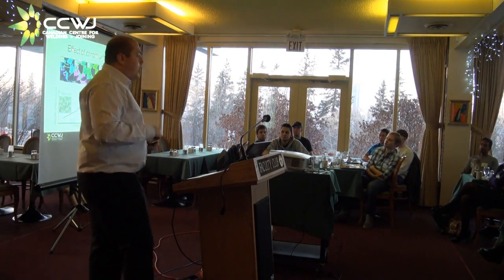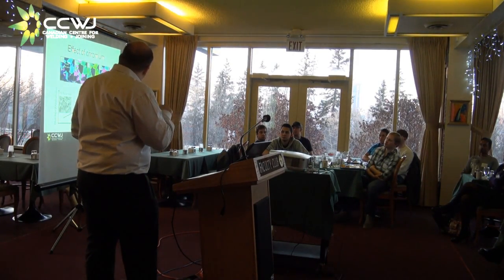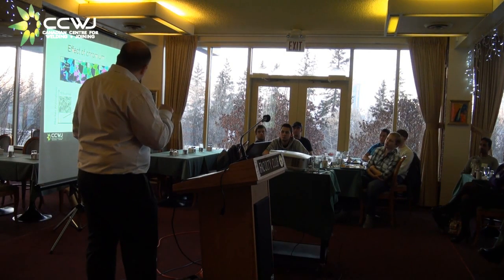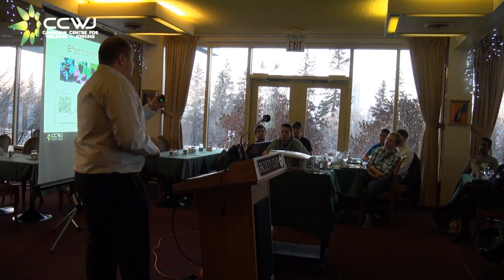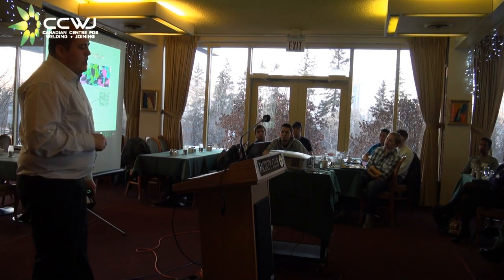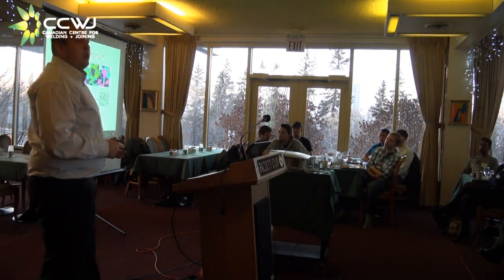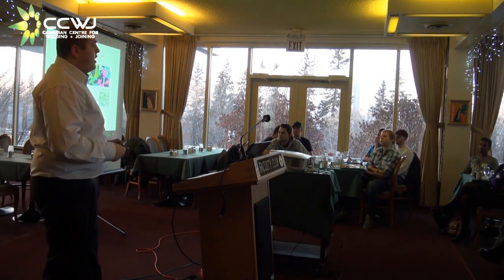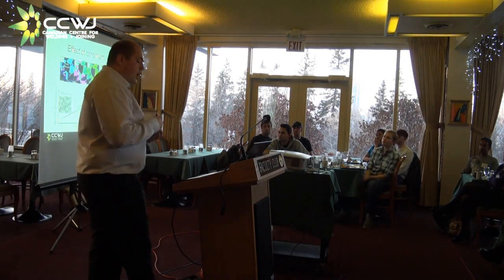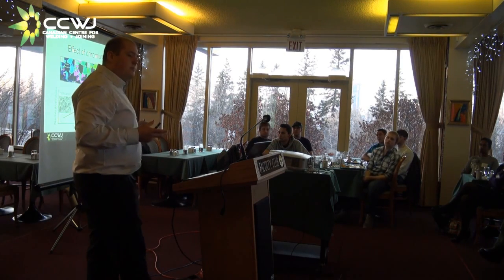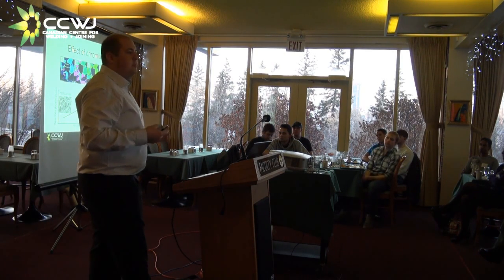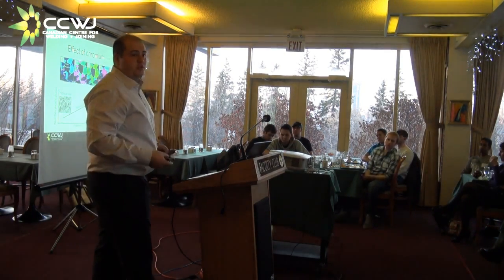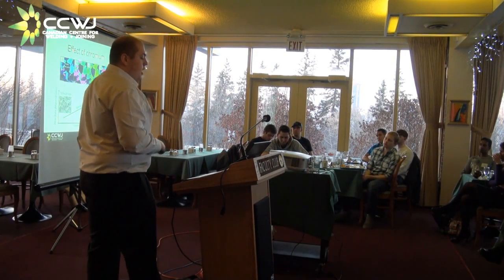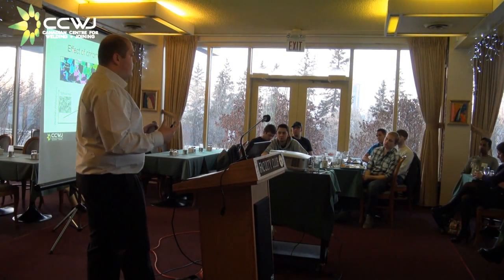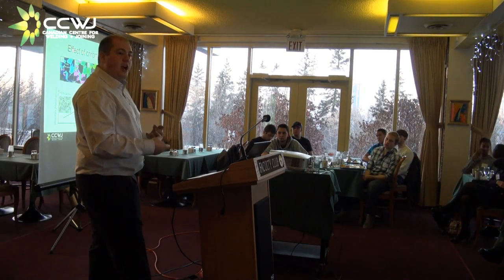And that would give these kind of secondary phases here that contain chromium, nickel, silicon, tungsten, and a host of other little special ingredients, which were extremely brittle. They really cracked very easily under loads. So now the periphery of our carbide would be susceptible to the wear of the oil sands, in addition to dissolving the carbides and decreasing the fraction.